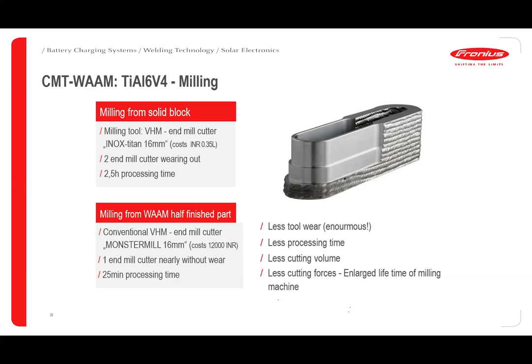So what I would like to tell you here is that people who have already worked with titanium know how difficult it is to machine. But when we do it with this WAAM process, we experienced low tool wear, less processing time, a very low cutting volume, and very little cutting force, particularly with respect to usage of the end mill cutters, because we were able to use only one end mill cutter to process the component from the WAAM. So this gives us further confidence that if you want to machine also, it is possible, and you will be able to get a very trouble-free kind of deposit onto the structure.